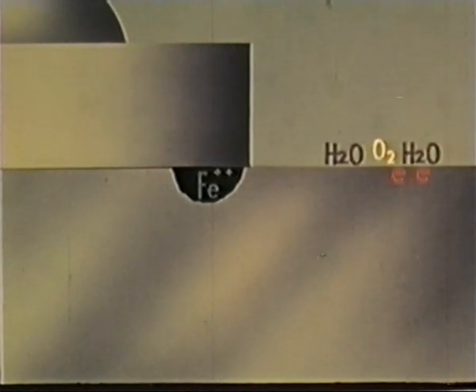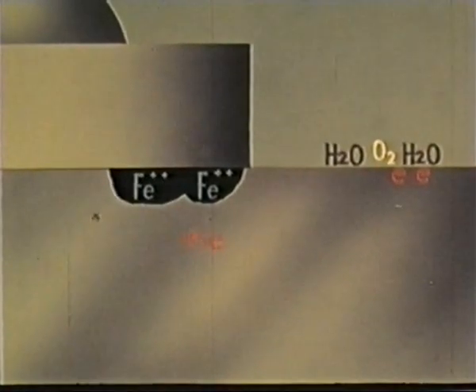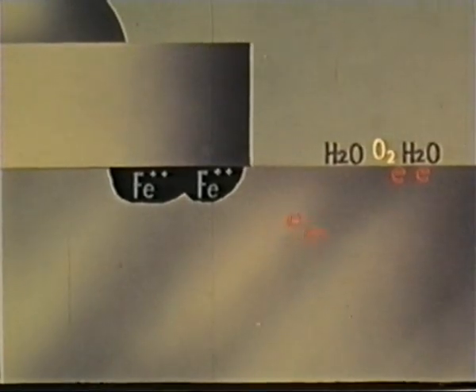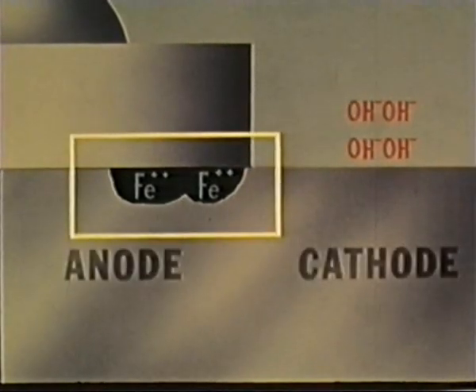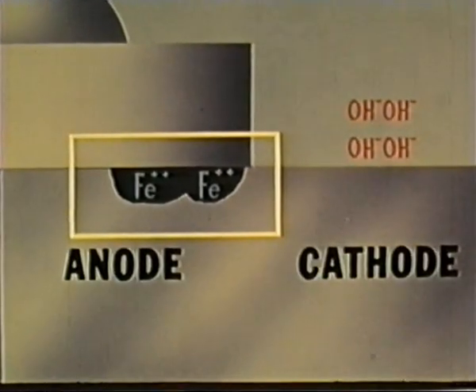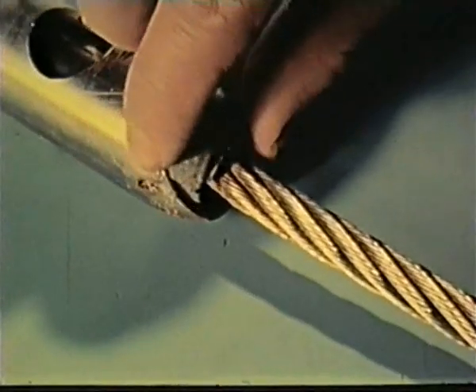Thus, should the supply of oxygen at any point on the metal surface be insufficient to maintain passivity in a chloride-containing environment, as a result of local shielding, a small local active area would develop, creating a large potential difference between it and the surrounding passive area. The result would be galvanic action between the small active area as anode and the large surrounding passive area as cathode, with intense corrosive action at the small active area.